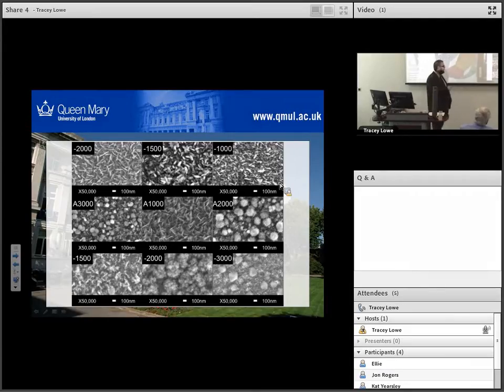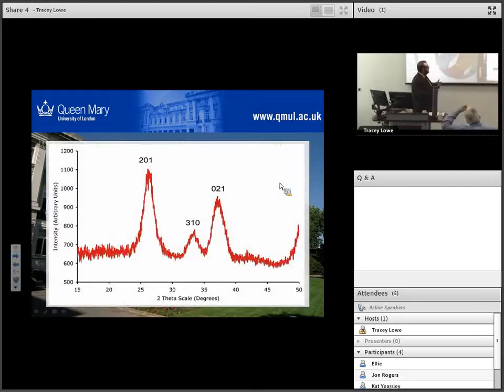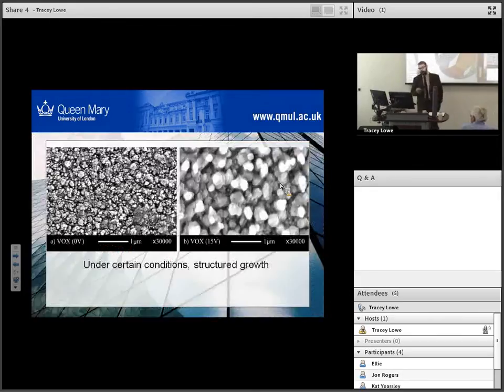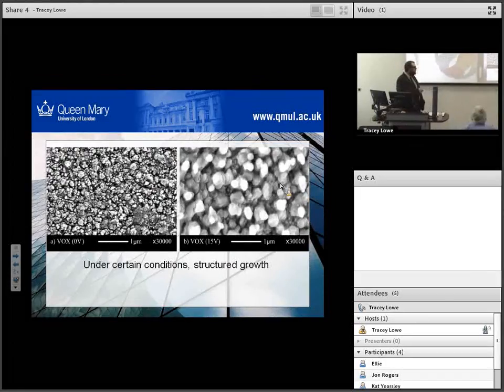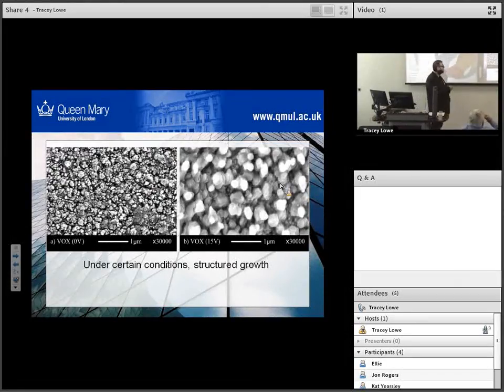We can make a whole bunch of different structures that seem to have a somewhat higher surface area than the bog standard AA-CVD grown film. Again you see an X-ray pattern indicative of a small crystallite size. Under various conditions we can get structured growth. So this is our bog standard AA-CVD, and this is one of our films where we've got some structuring, some sort of pseudo hexagonal type thing going on.